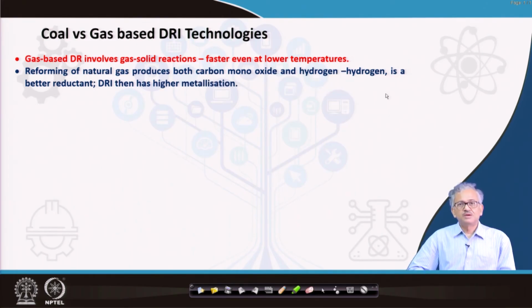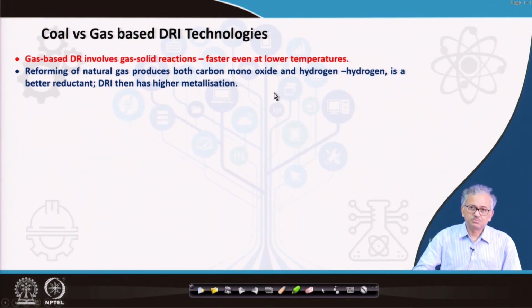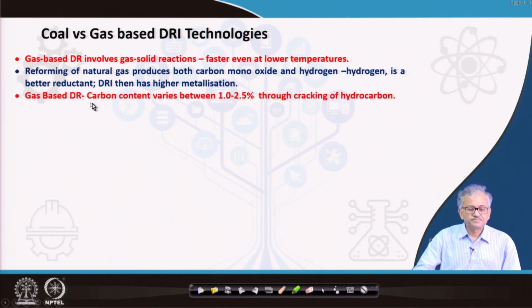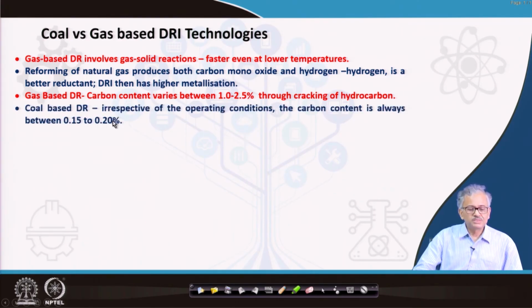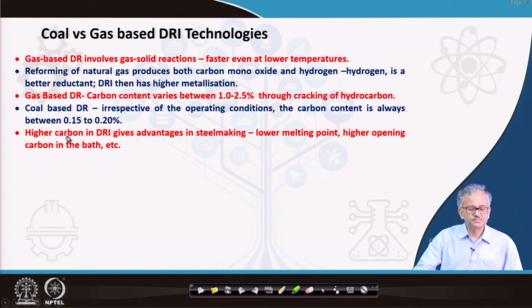Reforming of natural gas produces both carbon monoxide and hydrogen. Hydrogen is a much better reductant compared to carbon monoxide, both thermodynamically and kinetically. That is why the DRI of the gas based process has higher metallization. In the gas based process, the carbon content of the DRI can vary from 1 to 2.5% through the cracking of hydrocarbons. Some special technology is there: during the cooling of DRI, hydrocarbon cracking takes place, which deposits carbon on the DRI. So, gas based DRI has higher carbon content, so its liquidus will be lower. Coal based DRI, irrespective of the operating condition, always has carbon content between 0.15 and 0.2.